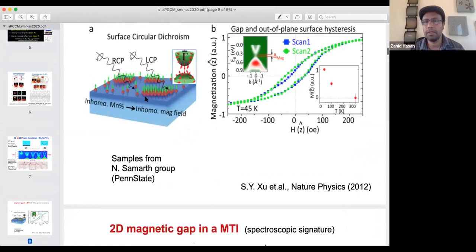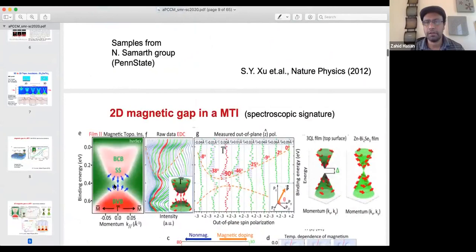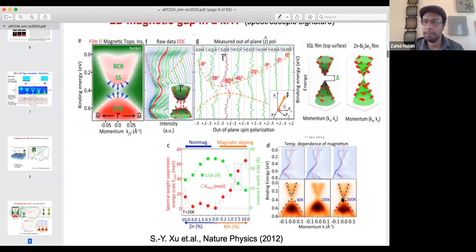So you see, there's a lot of spectral weight. It's not green, this area is white. So even at low temperature, there is a lot of disorder. So the gap in momentum space is affected by disorder. It's only kind of an average gap, and that doesn't fully cleanly disappear. But part of it is also, this particular plot, it may be thermal broadening. So we see spectroscopically that it's disappearing, but it could be thermal. Of course, thermal broadening is part of the intrinsic physics. But the short answer is that it doesn't directly correlate with TC. It always persists above TC. Sure. In spectroscopic measurements, yeah.